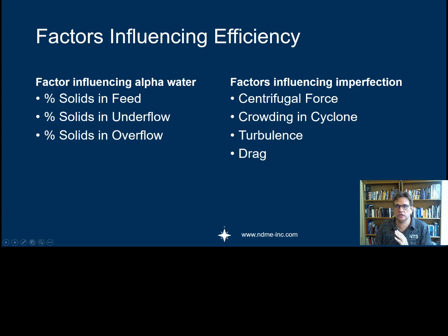I personally would focus far more on alpha water as a practical metallurgist than trying to get this perfect separation going. And typically, a vendor is not going to quote you an imperfection factor of better than 0.35. So you're not going to score much out of it.